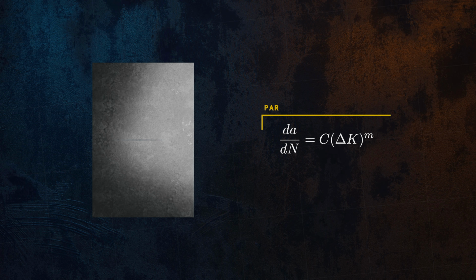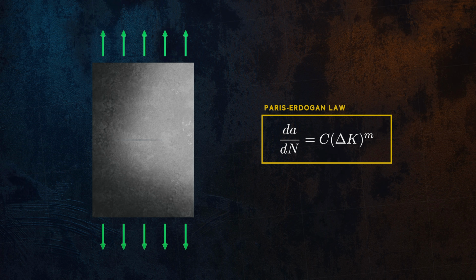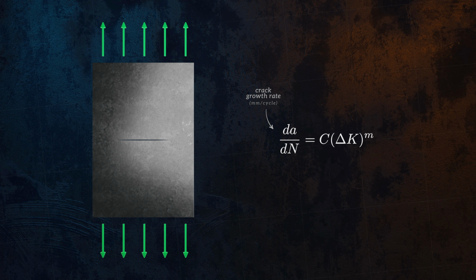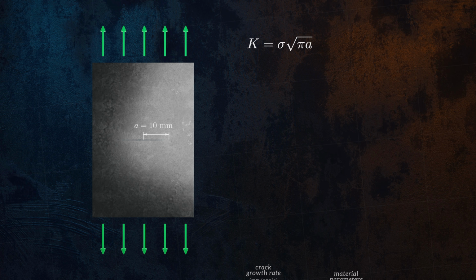It tells us that the crack growth rate, the amount the crack advances per cycle, is governed by the range in stress intensity factor experienced during each cycle. C and m are material parameters determined experimentally. Consider a crack with a measured half-length a of 10 mm. When loaded with a cyclic stress that fluctuates between 20 and 200 megapascals, it sees a stress intensity factor range of around 32 megapascal root meters.